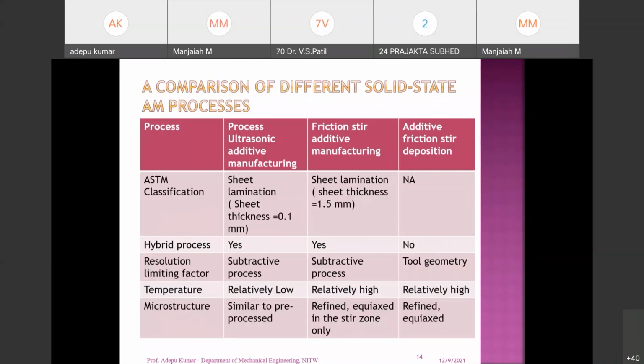So I am giving a comparison between these three processes as per different criteria. For example, as per ASTM classification, in ultrasonic additive manufacturing the thickness of the sheet is on the order of 0.1 mm, and it also requires a good surface finish. Whereas in friction stir additive manufacturing, a minimum of 1.5 mm thickness is sufficient. Whereas in additive friction stir deposition, there is no sheet. We can use some other techniques to deposit the material over it.